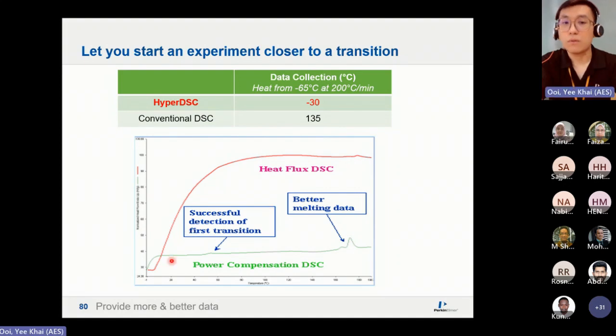For those familiar with DSC, usually you have a transient point or the starting point. Any transition here you cannot use as data because it is overlapped by the equilibration period of the furnace. For heat flux DSC, it takes longer until it starts the first data capture. But for power compensation DSC, the equilibration period is much faster, and you can detect the first transition at a much lower temperature, which you don't see in heat flux. There it is being overlapped by the equilibration period, so you cannot determine it. The signal is also much better for the second transition. This is why we say power compensation DSC has better sensitivity and the fastest equilibration period, due to the furnace design.